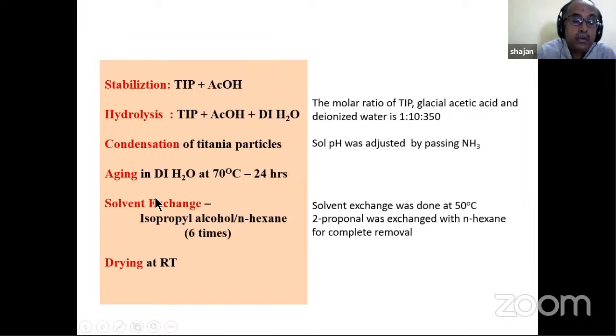As I already told you, we are using n-hexane and isopropyl alcohol to reduce the surface tension, because we are using water here. These two have a surface tension lower than water. We do the solvent exchange 6 times until the solvent is completely exchanged, and then it is dried at room temperature, around 30-35 degrees centigrade, and we get the aerogel.